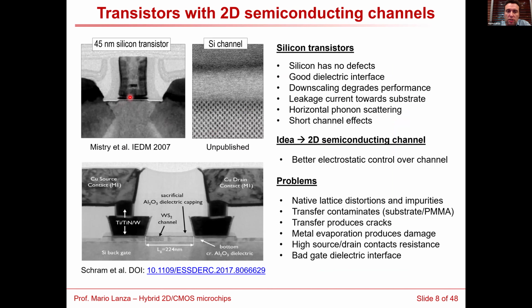Here you see a cross-sectional TEM image of a silicon transistor with the source, drain, and the gate, and here you see the bulk silicon. If you zoom in here, what you observe is that the silicon lattice is almost perfect with the silicon dioxide insulating layer and the top gate. And this works very well.